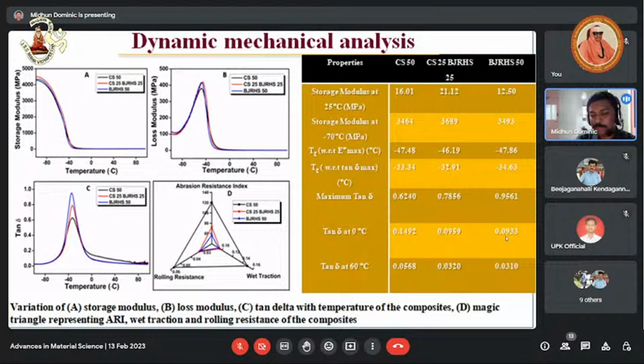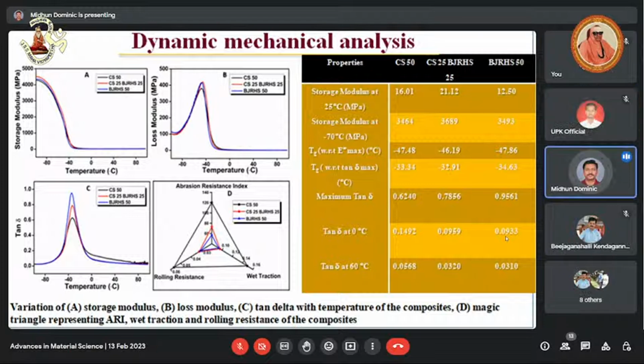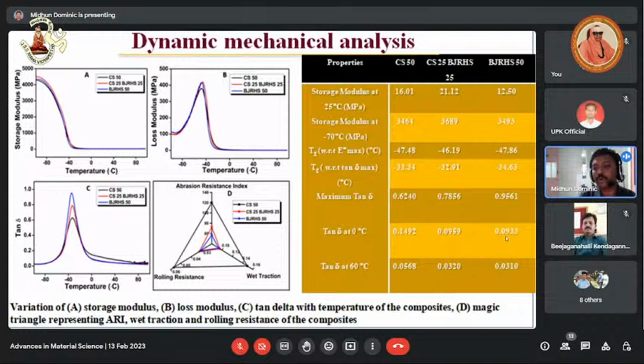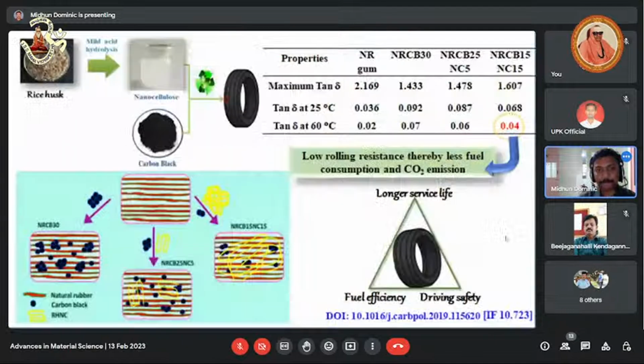So this paper summarizes that we can make use of this BJRHS to decrease the tan delta at 60 degrees Celsius, to decrease the rolling resistance. But we have to compromise on the other mechanical properties. So we have to develop another strategy to synchronize with carbon black to lower tan delta at 60 degrees Celsius with excellent mechanical properties.